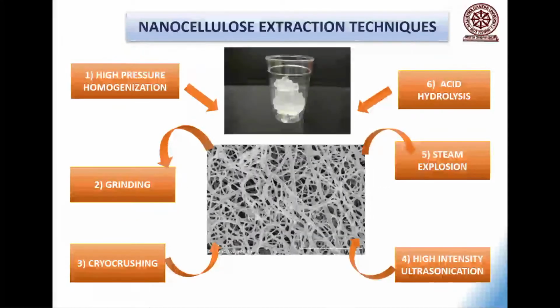How do you make them? The manufacturing technologies are now matured. You can do acid hydrolysis. You wash the material with an acid. Acid can remove all the amorphous part, lignin, hemicellulose, waxes. You can do steam explosion process. You can do high pressure homogenization process. You can do grinding invented by the Japanese colleagues. Cryo crushing, you decrease the temperature and make the fiber brittle and you go for the crushing process. High intensity ultrasonication. So all these techniques have been matured now.